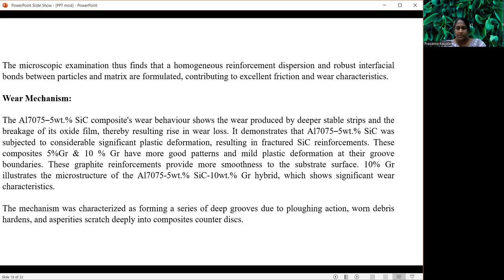whereas the standard SEM images of the sintered samples of aluminium with 5% of silicon carbide show the composite's wear behavior: the wear is produced by deeper stable strips and the breakage of its oxide film, thereby resulting in a rise in the wear loss. So it demonstrates that the 5% silicon carbide was subjected to considerable plastic deformation. I'm talking about the case where graphite is not being added.